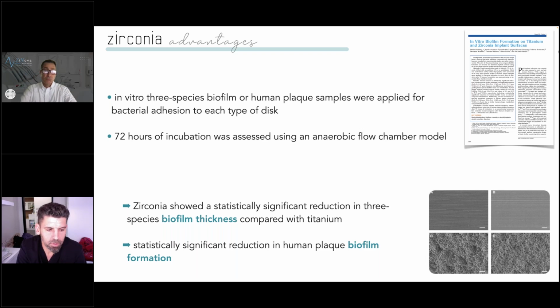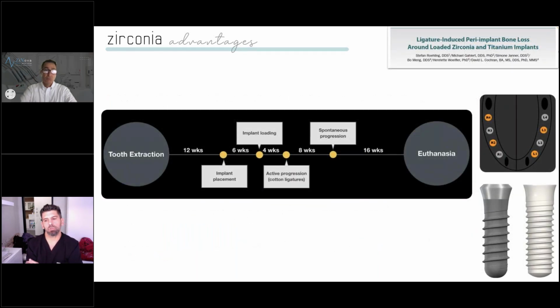And at the end of the study period, they showed that zirconia had a statistically significant reduction in all 3 species of biofilm thickness compared to titanium, and also a statistically significant reduction in human plaque biofilm formation. What this tells us is that zirconia is a more biocompatible material, less prone to accumulate plaque and bacteria, and because of this leads to a lower incidence of peri-implantitis.